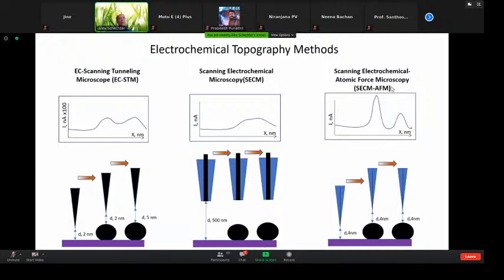It's called SECM-AFM. Now, the problem with the EC-STM is that there is a bias between the tip and the surface. And the distance is very narrow. It's 2 nanometers. But you cannot control a reaction and control the distance at the same time, because the control loop is controlling the distance by measuring the current. Now, if you measure both the position current and the reaction current, you have a mixed current. So you can never tell whether the abrupt increase in the current is coming from, let's say, a particle, or it is because there is a change, or from the reaction, for example. So this method is not suited for reactions.